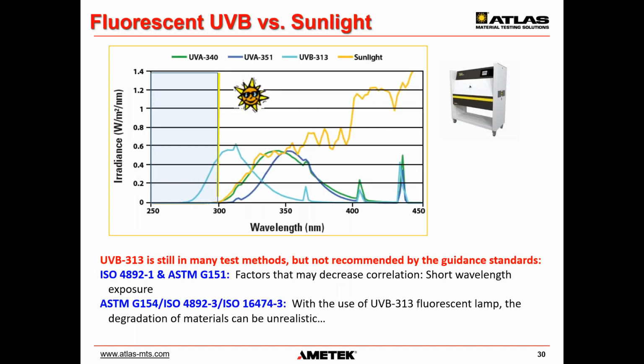UVB 313 bulbs, as used in fluorescent UV devices, were the original lamps used for those exposures. This dates back to an earlier testing philosophy that if a material passes this test, sometimes referred to as the bigger hammer approach, it could not fail in normal sunlight.